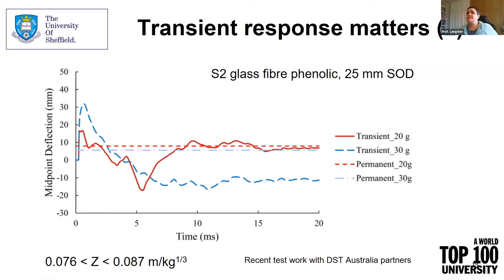And unlike the other panels where the reverse snap through buckling seems to result in a permanent deflection in the negative direction, in this case, you can see that after 10 milliseconds, the transient deformation has returned to practically zero, practically the permanent deflection. So you can see there's quite a difference in the two types of response that you see transiently, that if you didn't have the transient measurements, you would think that the responses were very similar in the two panels because the permanent deflections only vary by a couple of millimeters.